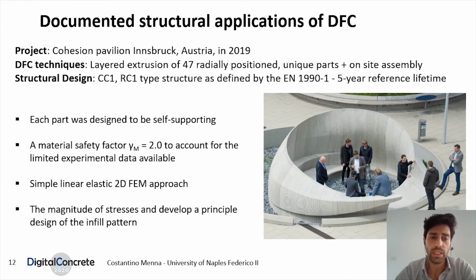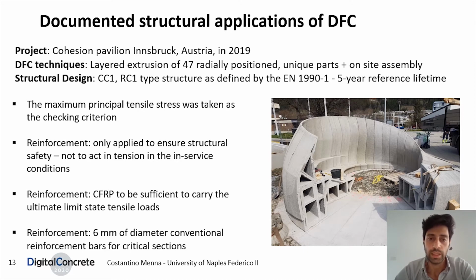To make the design simpler, each printed part was designed to be self-supporting. Even though the layered extrusion gives rise to very specific mechanical properties of the material, here a more conservative approach was pursued, and a material safety factor equal to 2 was considered to account for the limited experimental data available. The structural design was supported by a simpler linear elastic finite element model, and the outcome of this finite element calculation was used to develop a stress-based principal design of the infill patterns. Moreover, the principal tensile stress coming from the finite element simulations was used as a checking criterion against the tensile strength of the material adopted.